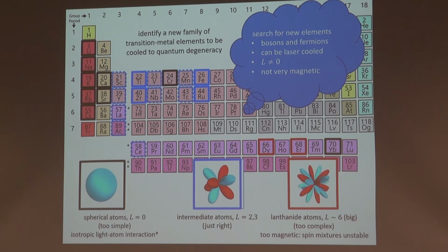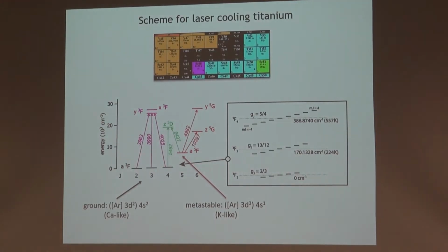And on deeper thought, we've also figured out that all these other atoms are also laser coolable by the same idea. So now there's maybe a dozen or so elements that people have not really worked with yet that I think all can be efficiently laser cooled with reasonable laser light in wavelength ranges between about 550 and 350 or so. And at least the laser cooling stage of producing ultra-cold gases, I think, is manageable for all these atoms. And so we're focusing at first on titanium.